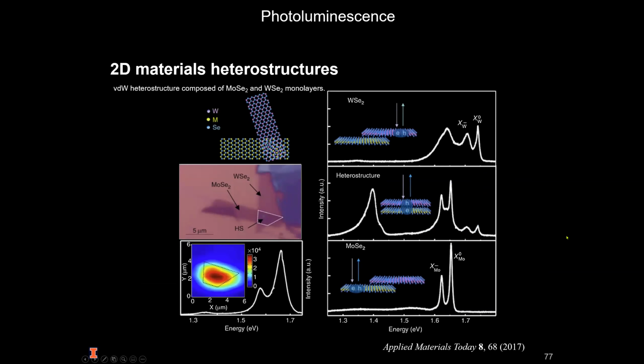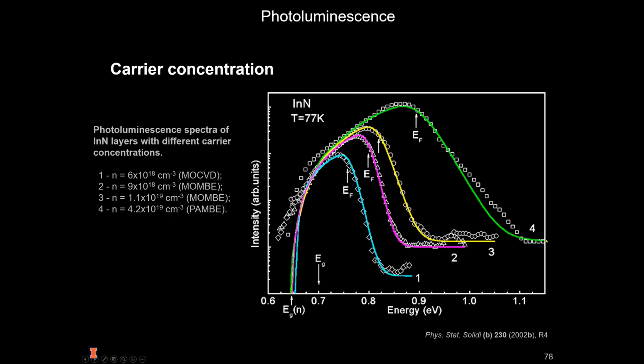The photoluminescence spectral line shape depends on the Fermi level energy and band broadening, so it can be used to assess carrier concentrations on our sample.